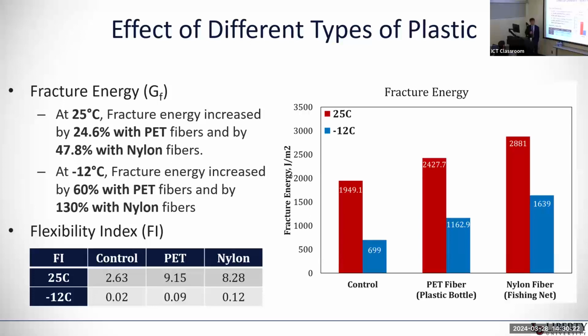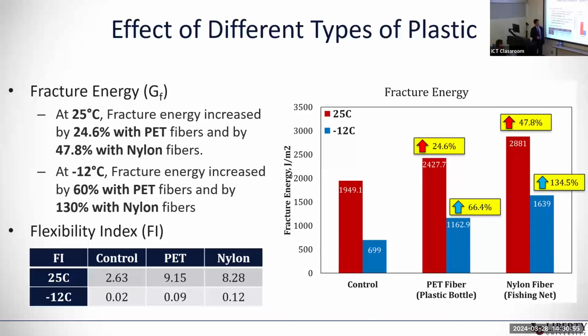So this slide shows the result of the fracture energy. This result is from the 5 millimeter by 20 millimeter PET fiber dimensions with 0.4% of the fiber content. As you can see here, as we add PET fiber, they improve the fracture energy at both 25 degrees C and minus 12 degrees C. Same for the nylon fiber. It improved the fracture energy by about 50% at 25 degrees C, and for the low temperature, it improved the fracture energy by 130%. It's a huge improvement of the resistance. We look at the FI value as well.